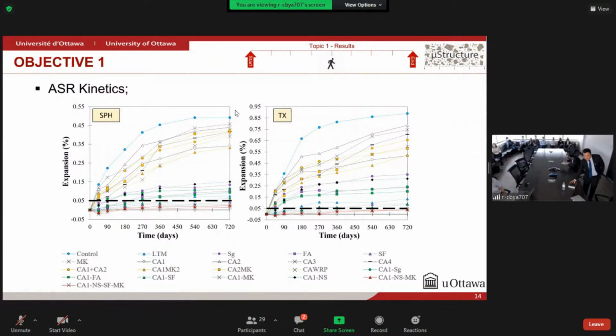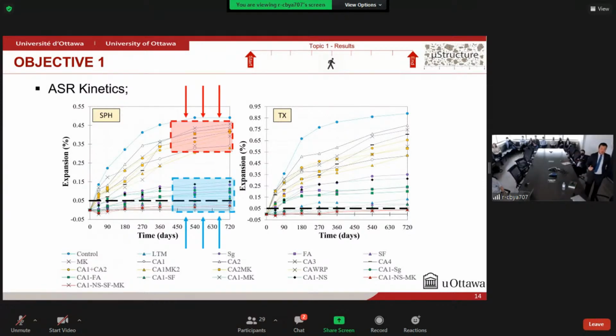As we can see here, for both aggregates, the overall results can be split in 2 main groups. In the first one here at the top, it's basically the concrete specimens in which we only add the different crystalline admixtures in the concrete. And in the bottom here, we have both SCMs made concrete and SCMs made concrete with crystalline admixtures. As we can see, all concrete mixtures were able to change ASR kinetics and expansion development.